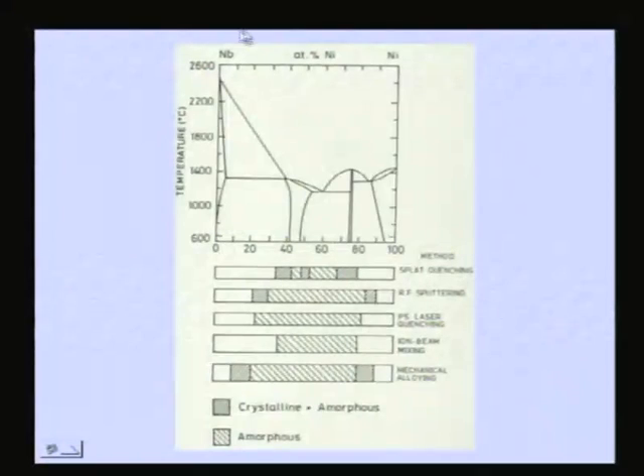So that means in case of nickel niobium, this is the composition, around 60%, where you can easily get a glass by splat quenching. For example, you can see this is the range by rapid solidification, whereas in case of mechanical alloying there is no such restriction. You can get it over a wide composition range.